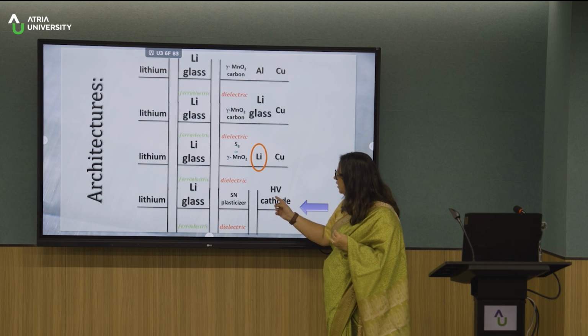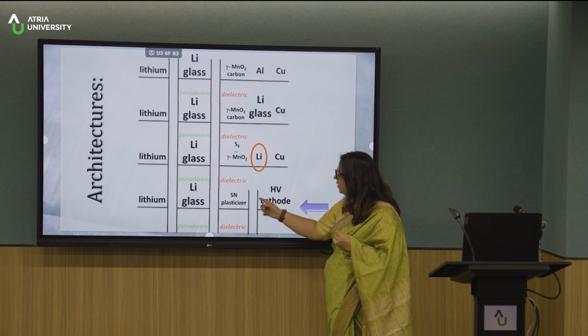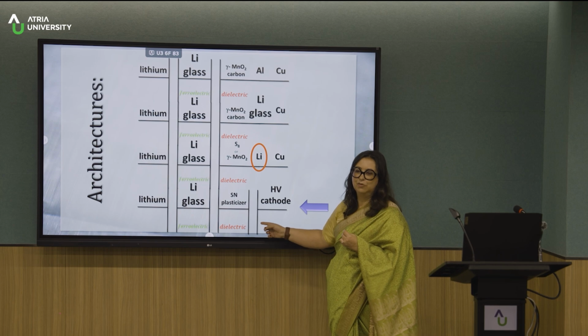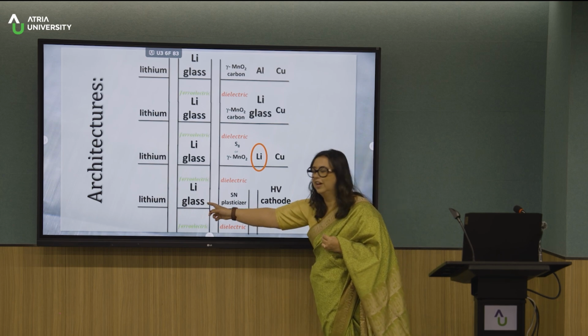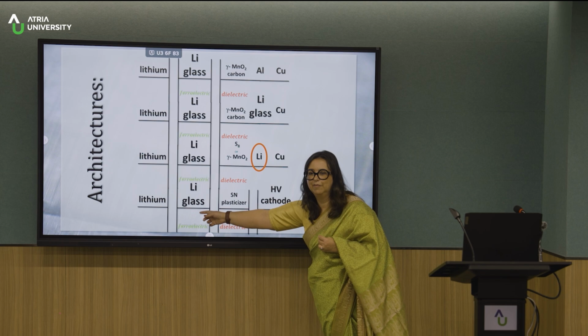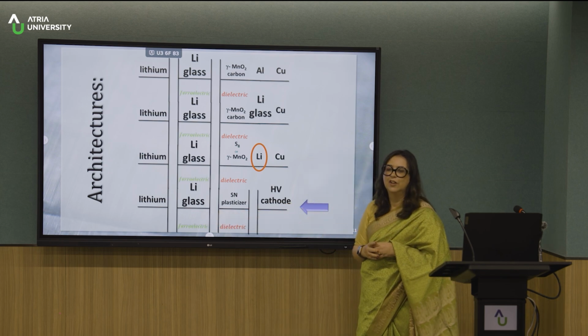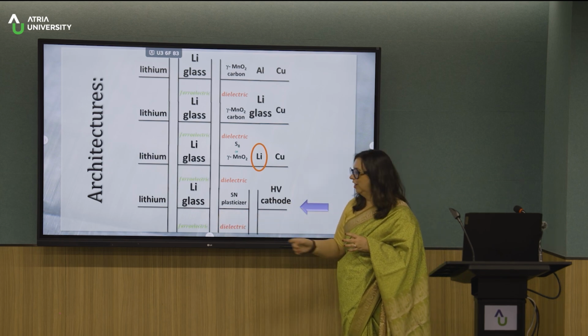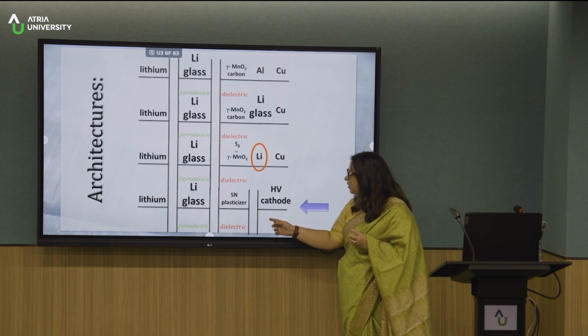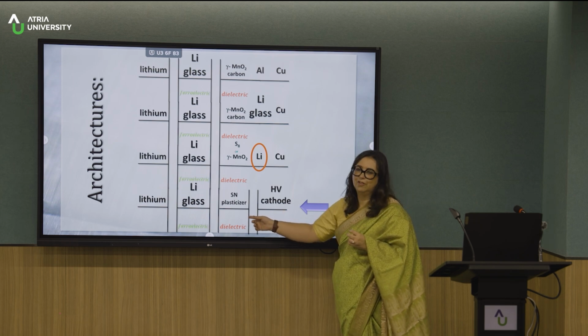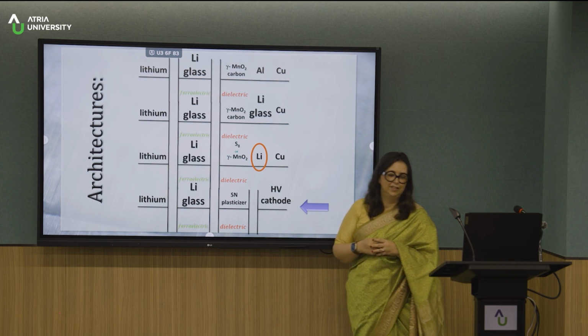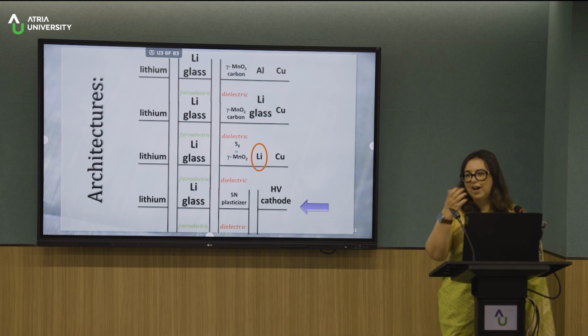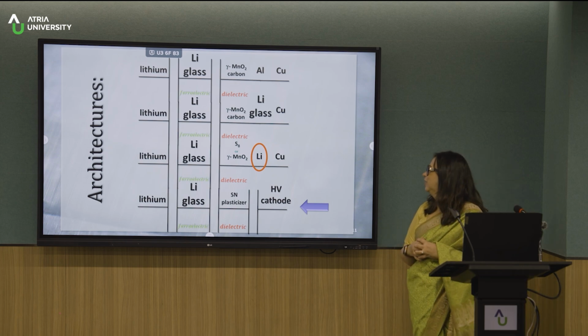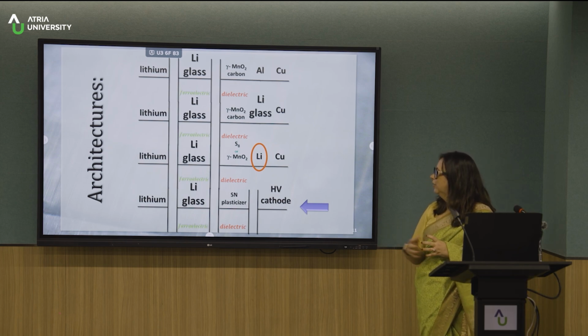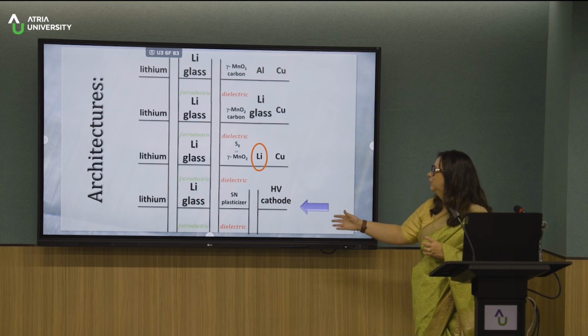But here, the idea is that the lithium will remain at the interface and will not cross, because I have the replenishment of lithium from the electrolyte. So the interfaces will be there, but it doesn't matter because I don't need to cross the interface with the lithium. So you are totally right, but that's what we are doing. We actually don't want to have that.